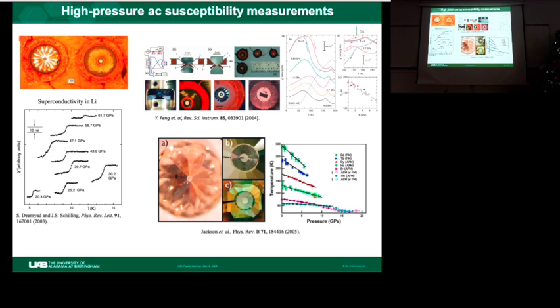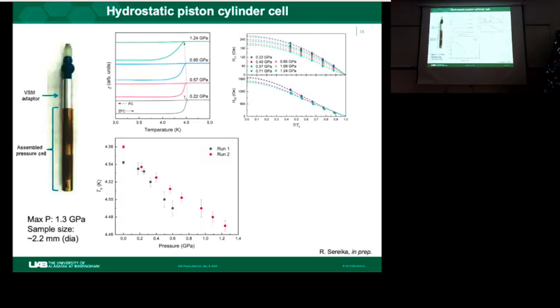This was done in Professor Schilling's lab, 20 years ago. And this beautiful data shows a clear superconducting transition under pressure. And if you manage to increase the filling factor, you can also track the magnetic ordering temperature under pressure and the type of magnetic order.